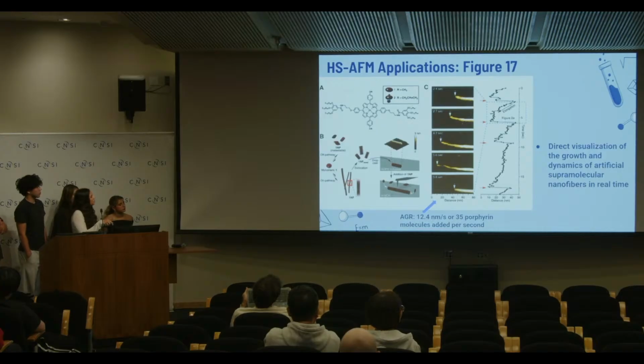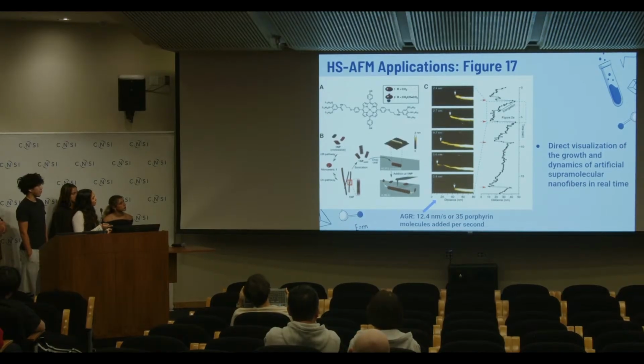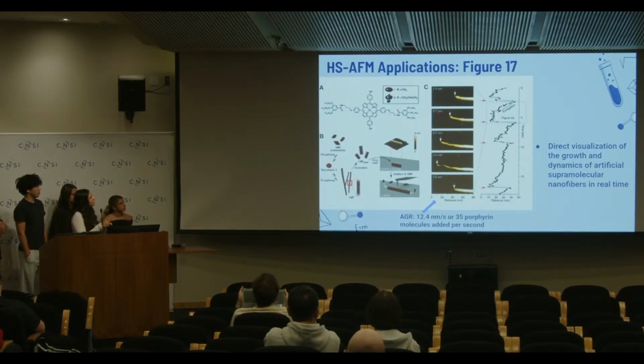So moving on to section C, you can see images of a nanofiber structure. What scientists did was they took preformed nanofibers called seeds, and they placed them onto a smooth, flat material for imaging. What they did next was they took the porphyrin 2, the nanoparticles, and they added it to the surface. What happened was that the nanoparticles assembled onto the nanofibers, and that's why you can see elongation in these images taken over time. This process is called seeded polymerization.